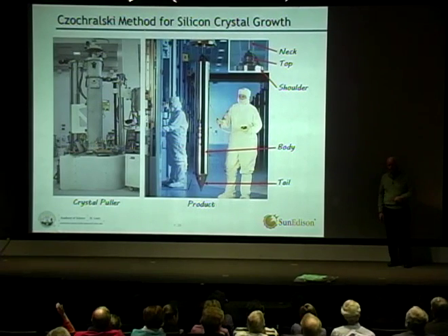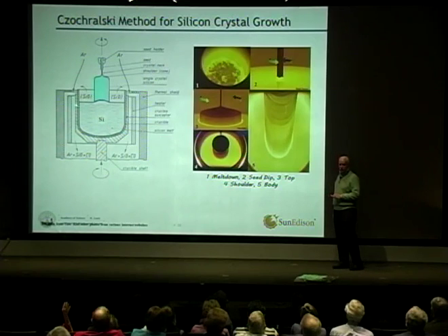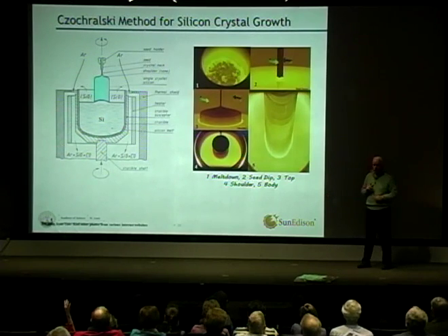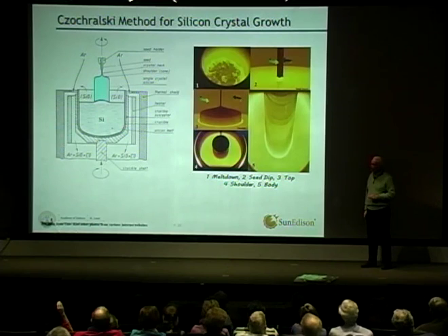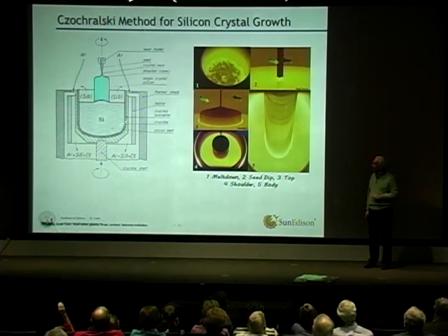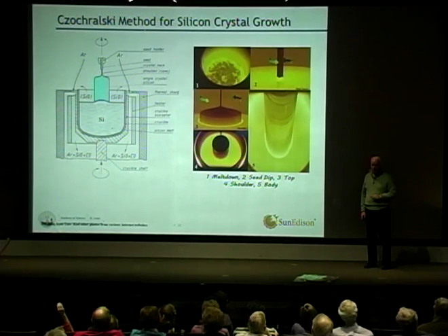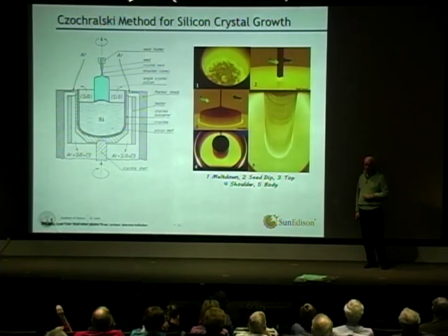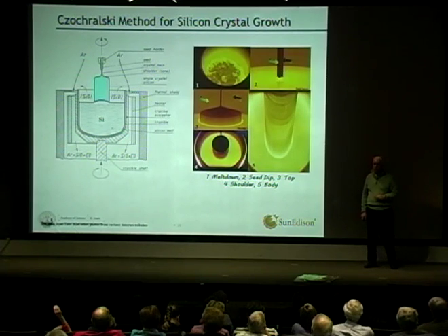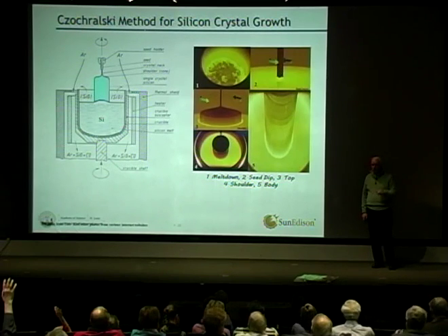Yes, ma'am? Yeah, so the doping is right here. We add the phosphorus or boron to the melt, and it's a very tiny amount. What we actually do is we buy some dopant material, which is silicon with a small amount of boron in it, or silicon with a small amount of phosphorus in it, and we add that to the melt here. I said there are 10^22 atoms per cubic centimeter. You're typically adding on the order of 10^15 or 10^16 atoms per cubic centimeter of dopant. So 10^16 would be about one millionth of the concentration.